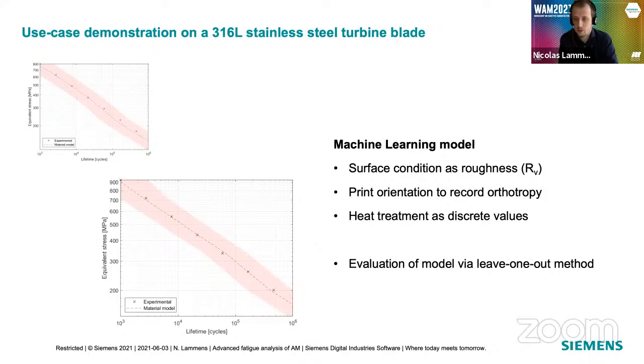And the input parameters that we considered in this study were just the surface condition, so we looked at the roughness of each sample, the print orientation, because we wanted to account for orthotropy in the material, and the heat treatment that was applied to the samples. The pictures you see on the left are two actual results from our machine learning using a leave-one-out principle. And what that means is that from all the S-N curves that you have from testing, you take one out of the training data.